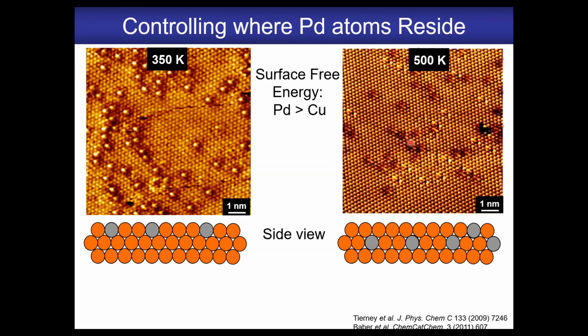But then what we know from high pressure XPS work, for example, is that if you have a surface like this with a catalytically active element under the surface or in the core, if you run a reaction over the top or flow things like carbon monoxide, those elements will actually be stabilized back at the surface. So the thing to remember is alloys are very dynamic, just above room temperature, in terms of how they respond in their surface composition as the reactive atmosphere is changed.